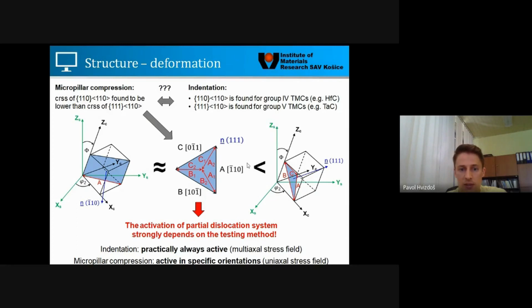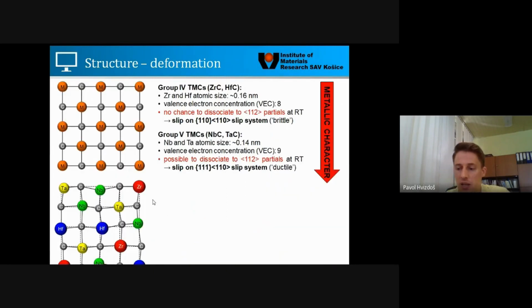However, in case of micropillar compression, because we had specific crystallographic orientation, we were not able to activate those partials, even though they should be activated during indentation. So that's why we got 110, not 111, for example, for tantalum carbide. So basically, what we got is the structure deformation relation, to our best knowledge.